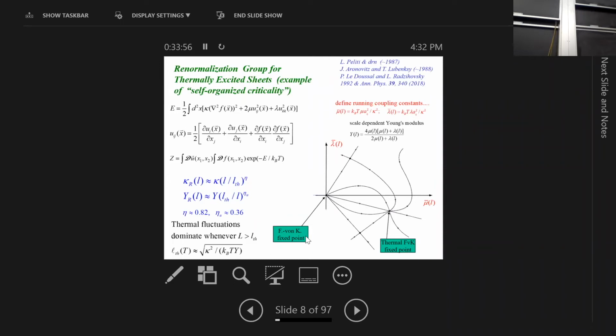So what about the cutoff at the length scale of the lattice? Here the graphene sample is about 0.3 millimeters square. Right, but fortunately, the physics that leads to these strange results happens not at short wavelengths, it happens at long wavelengths. So it's an infrared divergence. It's like critical phenomena where the details drop out and only appear maybe in this thermal length. So that's how we can get away with not looking at microscopic details. Those details are quite interesting and important, and they're going to come later in this talk as well. But that's why we can get away with this.